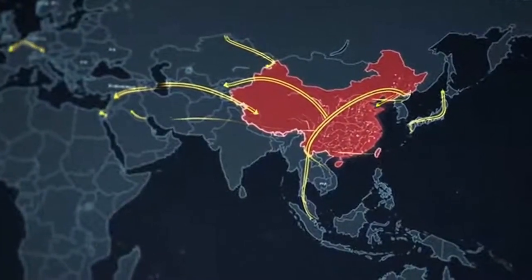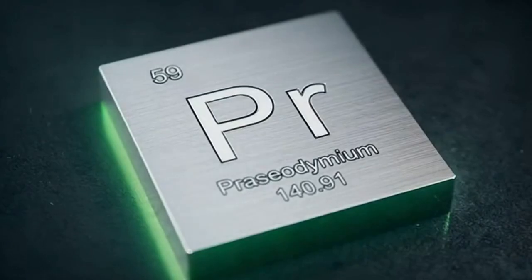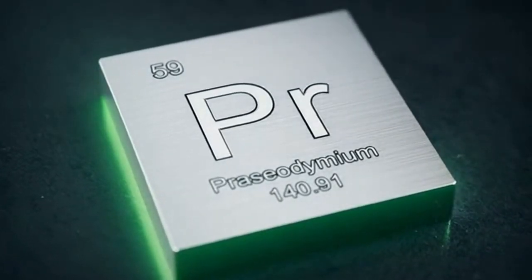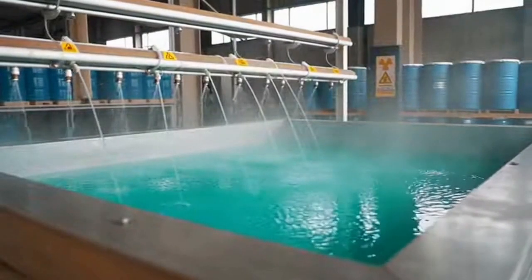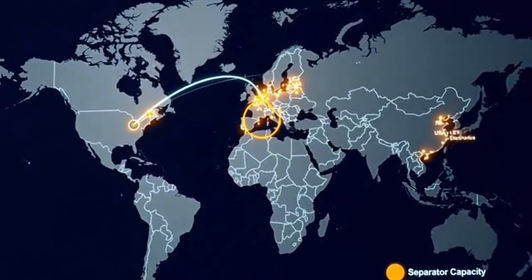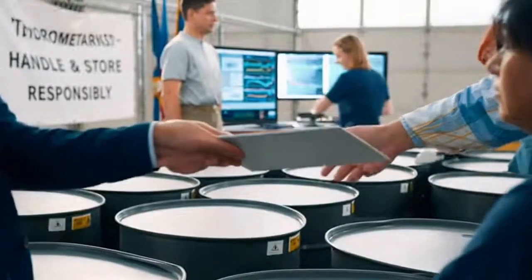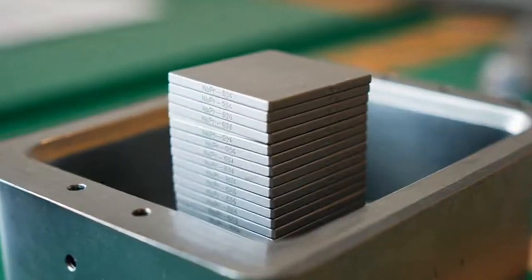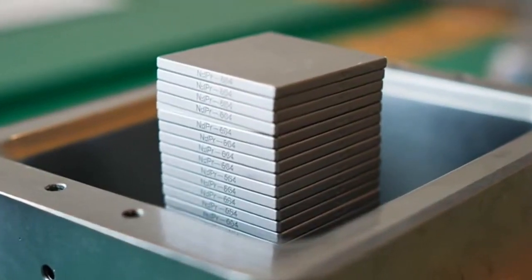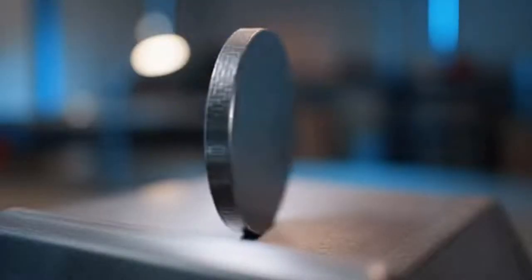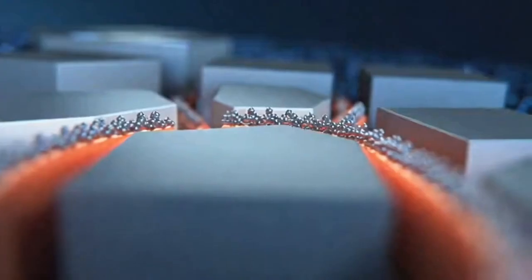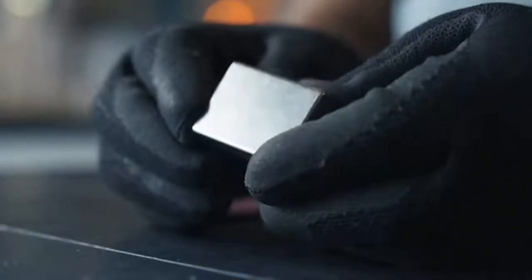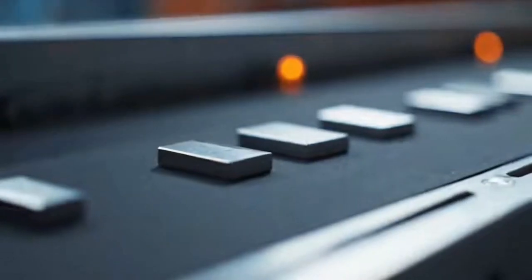They shifted from a monoculture of neodymium-forward alloys to blends with more praseodymium, paired with a disciplined grain boundary diffusion of dysprosium targeted precisely where it did the most good. Coercivity climbed at the temperatures that mattered. Saturation magnetization dipped a little, on paper, in a way no driver could feel. Field returns dropped. The pivot was not a press release. It was a revised spec sheet and a test cell that stopped producing heartburn. The lesson is not about any single element. It is about treating performance as a landscape, not a vertical line through one number at 25 degrees Celsius.